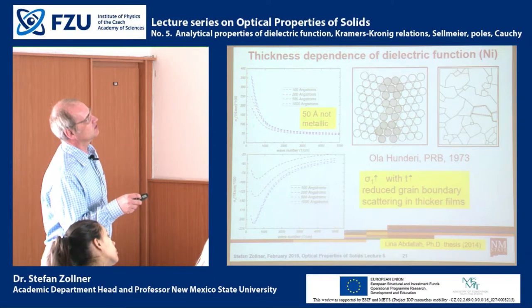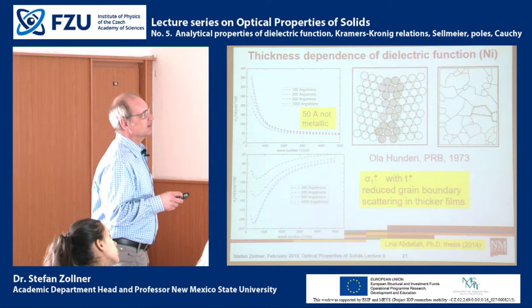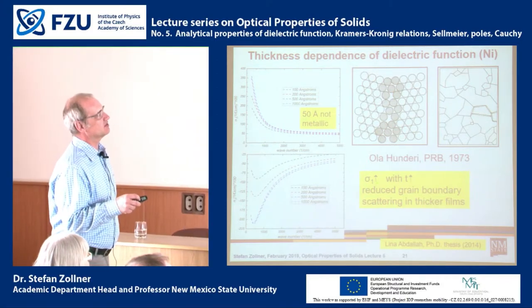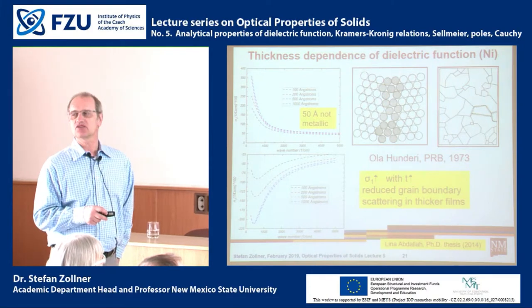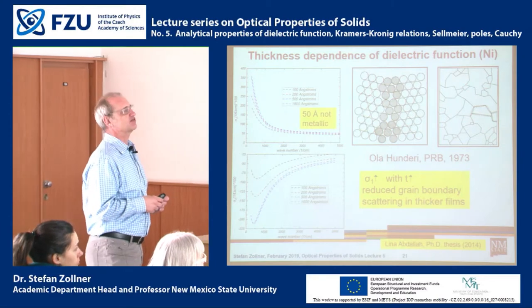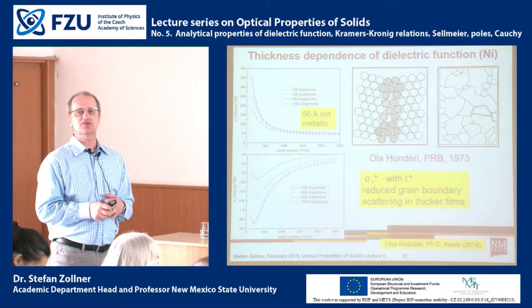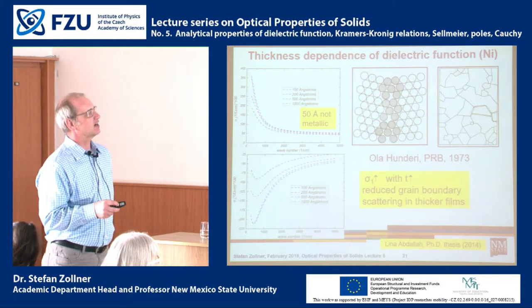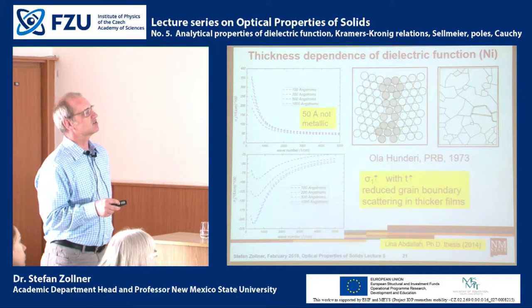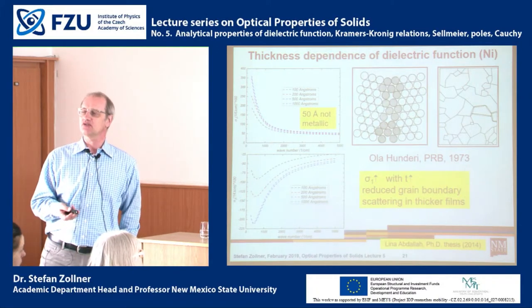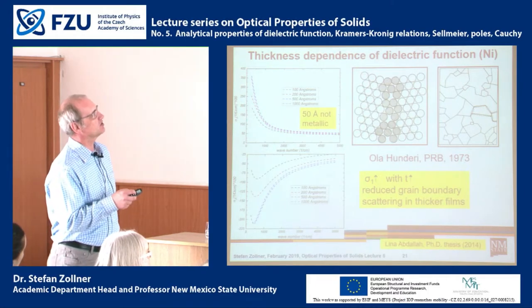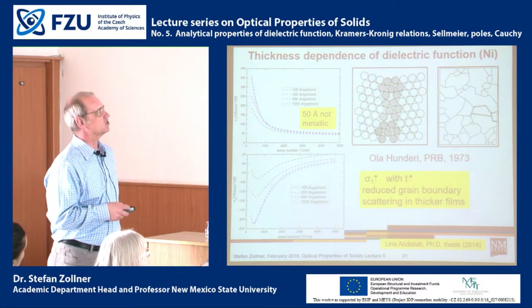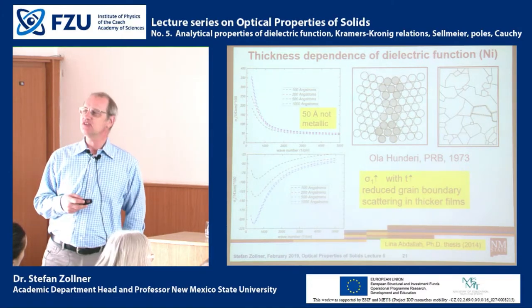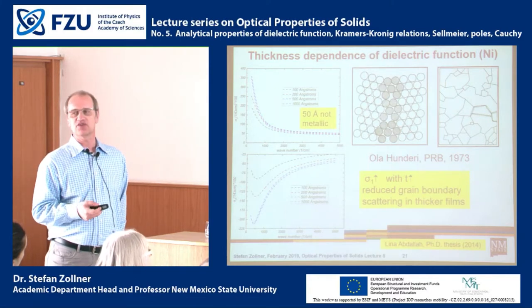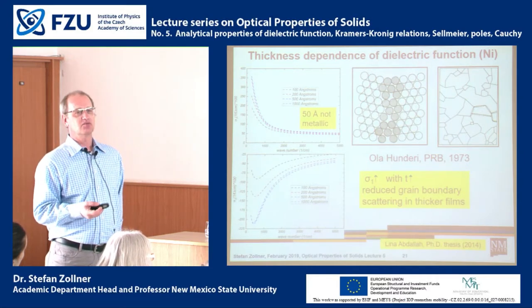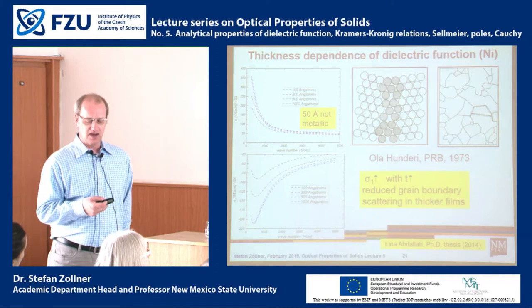The optical constants of nickel depend on the film thickness, and perhaps it should be obvious that the conductivity goes up as the thickness goes up. So if you have a thicker film, then you have less scattering at the bottom and top interfaces, and therefore the conductivity of a thicker film is larger. So you see this not only in electrical measurements, but also here in the optical measurements, we see a change in film thickness. So if you have a thin film of a material, you should never assume that the thin film has the same optical constants as the bulk, but it is important to characterize the optical constants of that film.